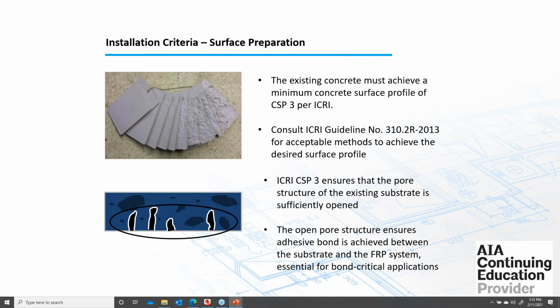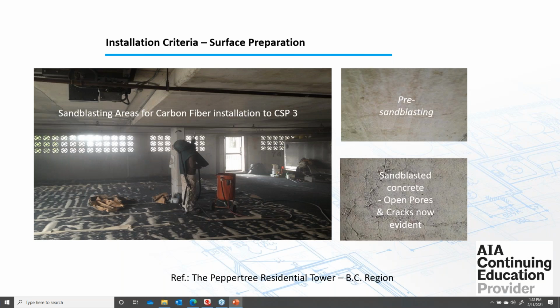The existing concrete must achieve a minimum concrete surface profile of CSP3 per ICRI. The CSP3 will ensure that the pore structure of the existing substrate is sufficiently open to ensure adhesive bond between the substrate and the FRP system, which is essential for bond critical applications such as flexural strengthening. Next slide. You can consult ICRI guideline number 310 for acceptable methods to achieve the desired surface profile.